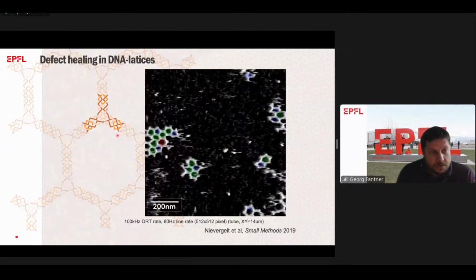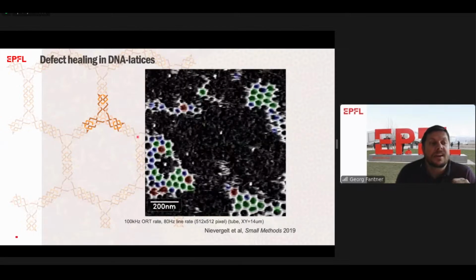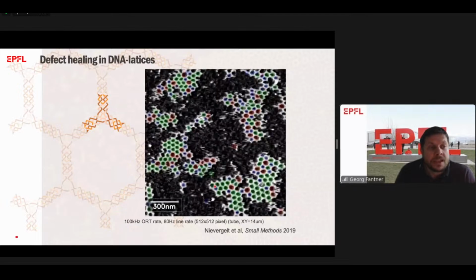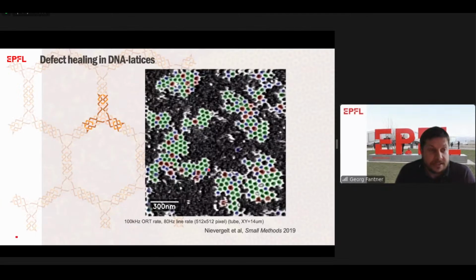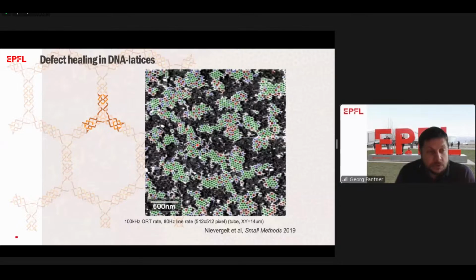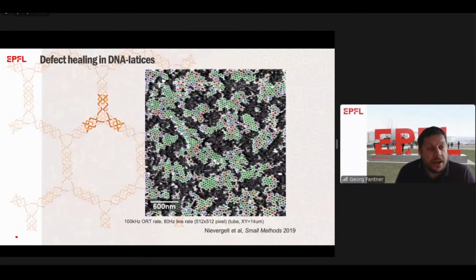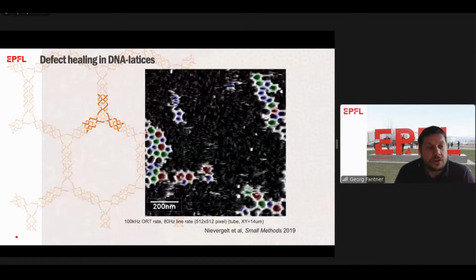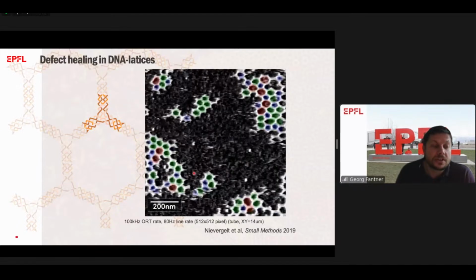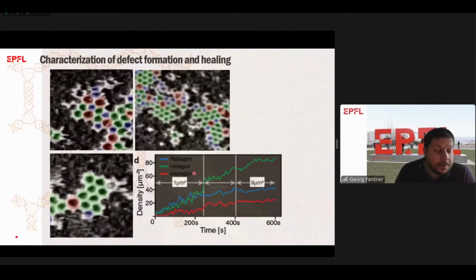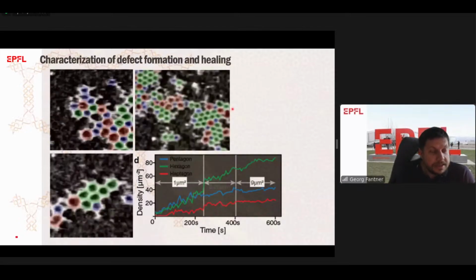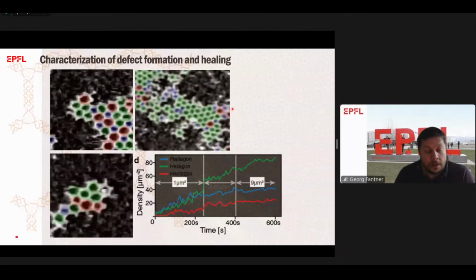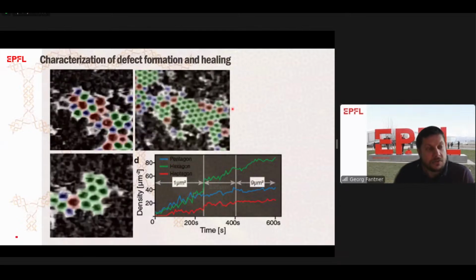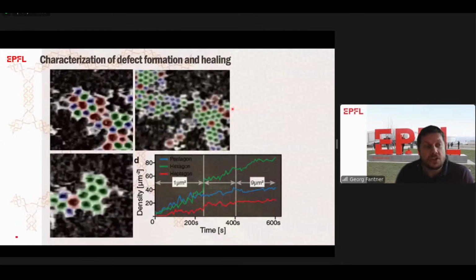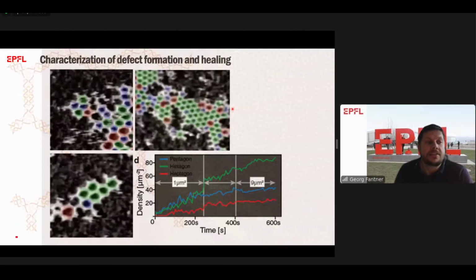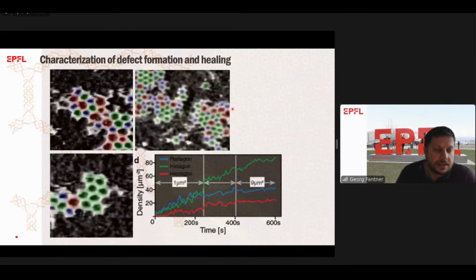We can then again use machine learning to identify what kind of structures these are making. The green ones are the correct six-fold symmetries in the hexagons, and then blue are 5 and red are 7. And you see that as a function of time, we actually get correction mechanisms within this self-assembly. Currently we're working on expanding that to explore the full phase diagram in terms of binding energies, lengths, and flexibilities, to really study the fundamental biophysics of such molecular self-assemblies.